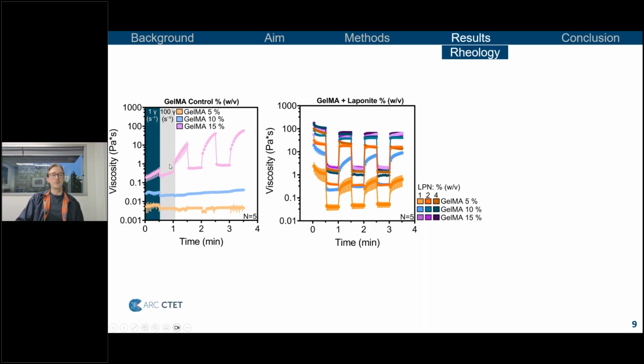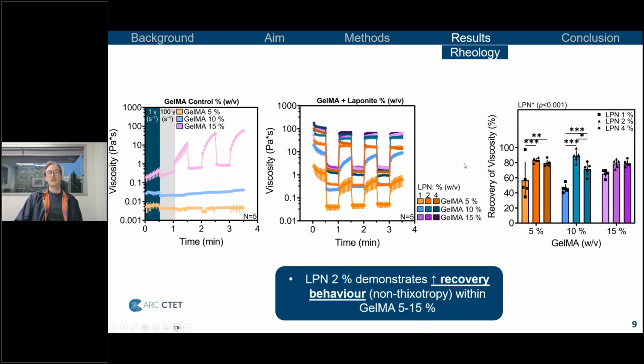In the GelMA 15%, viscosity is increasing over time due to the increase in shear rate and solidification occurring. We can then see when you incorporate GelMA and laponite that you get these nice instantaneous recoveries when you increase laponite in concentrations of specifically more than 2%. And when you characterize the recovery of viscosity, we can see that laponite 2% demonstrates increased recovery behavior compared to other groups, of approximately 80% across GelMA 5 to 15%.